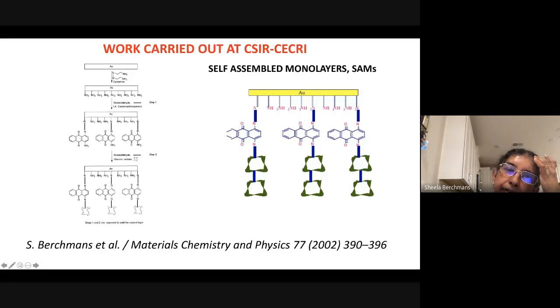The first strategy that we have tried is self-assembled monolayers. Self-assembled monolayers are monomolecular films of thiol molecules on gold electrode surfaces, which are formed without the help of any external force. So they self-assemble on gold electrodes in the form of a monolayer, and we try to make use of thiol molecules with suitable terminal groups like amino groups, carboxylic acid groups, and so on, so that to these terminal groups we can attach either a mediator or an enzyme to the electrode surface.